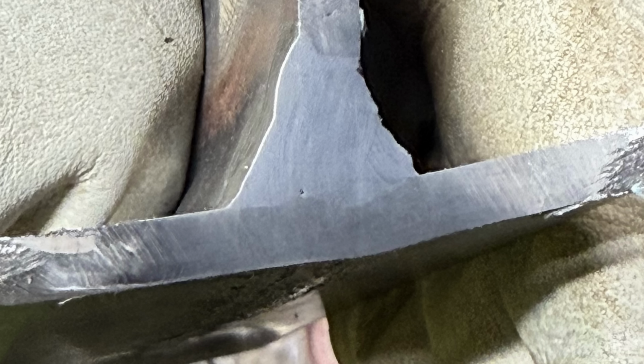Now defect-wise on this cut and etch, there's a little bit of a slag inclusion bubble there. Pretty typical. I didn't clean it the best when I went to cap it, so had I used a wire wheel and a pick and cleaned it a little bit better, I would have likely eliminated that. And keep in mind, when you're carrying a lot of metal vertical up, it's very hard for it to chew in and penetrate much and consume stuff like that little slag inclusion there. But from a strength perspective, that's of no consequence in this. That's not going to cause a failure. And like I said, this is non-critical stuff, so this is more than strong enough for anything that you would really need for non-critical.